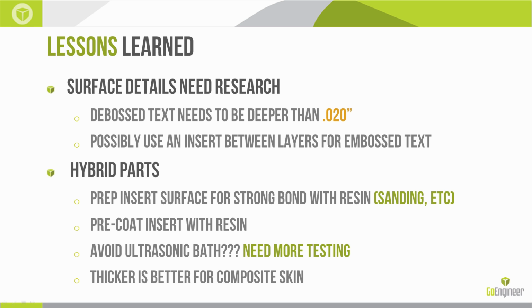And hybrid parts. For my last part, where I wanted to keep some non-soluble parts embedded, I need to promote a better bond between those. That might be roughing the surface up or pre-coating the insert with some resin to make sure it's got enough resin. Possibly avoiding the ultrasonic bath. The ultrasonic bath is much more aggressive on the parts, and that speeds up the removal of the support material considerably, but it also might affect the bond between, in this case, the ABS and the composite. And also, thicker is better for the composite skin. Thicker is going to be stiffer. Stiffer is going to reduce the chance of it changing shape or pulling away on us.